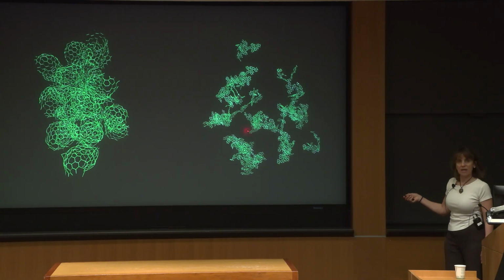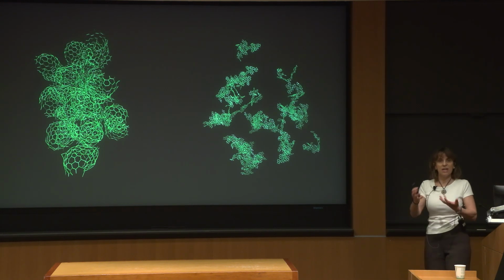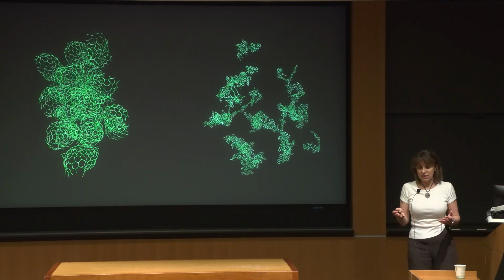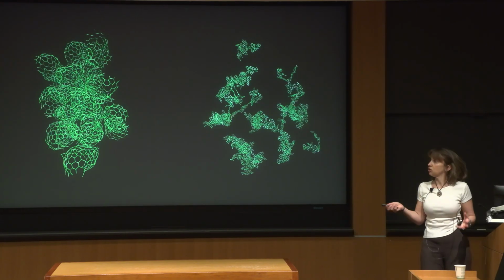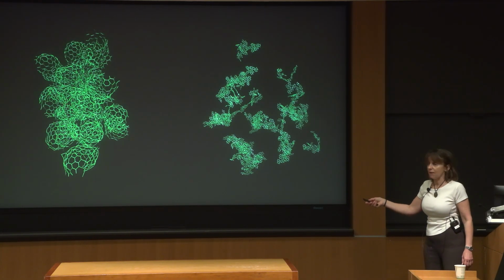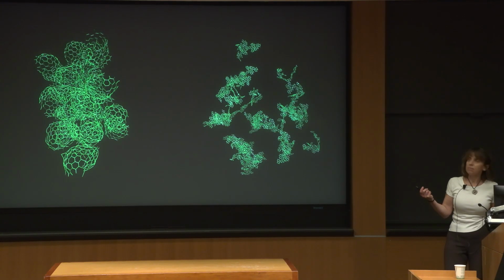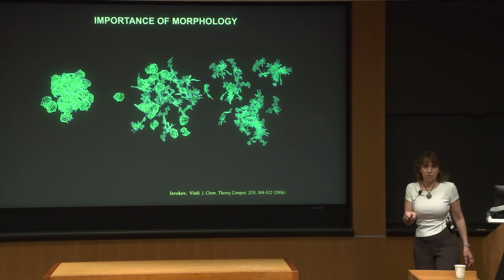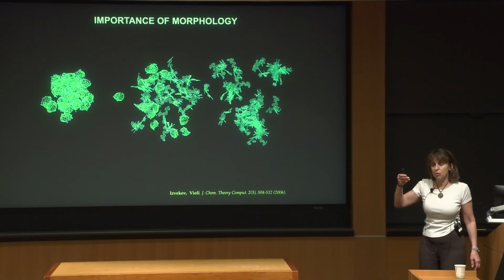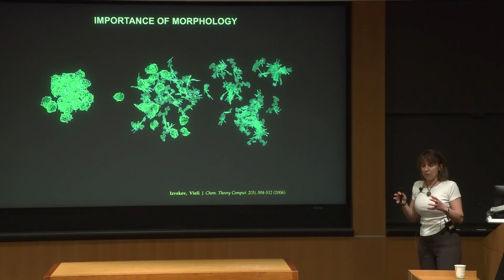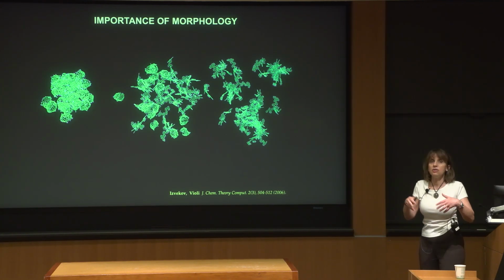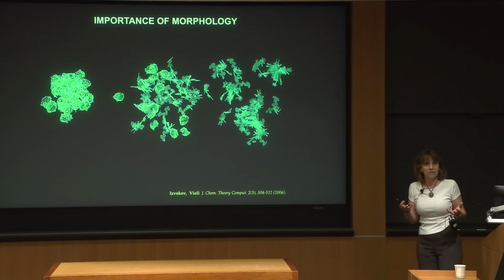You see subclusters. And do you know why? Because there is steric hindrance, because there is a curvature, they move. So the likelihood that they just stick together is much lower than here. Again, what this is telling you is that morphology plays a role in this case. So if I'm going up to primary, those nanoparticles, eventually they turn into soot primary particles, right?